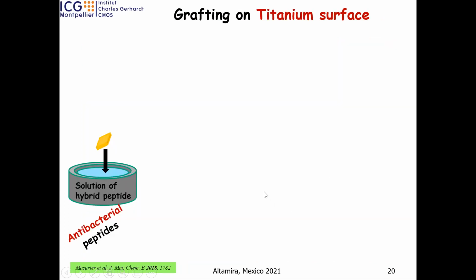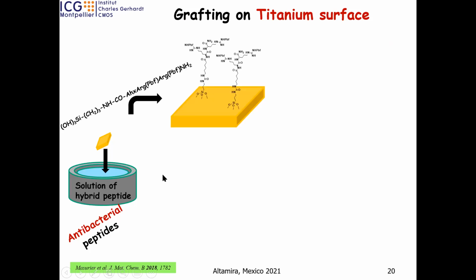It's possible to make the same strategy, but you can change the nature of the substrate. Now it's not SiO2, but titanium. Titanium, you know, is for prostheses. It's very important to make some prostheses antibacterial. And it's possible the same way, with colloidal solution and dip coating.